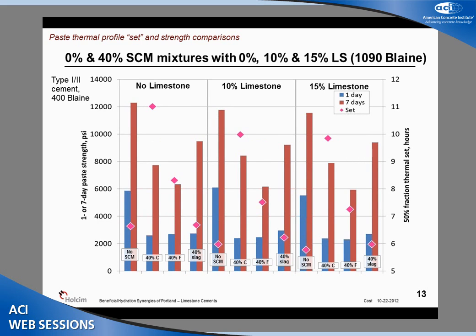Later on, we included some slag cements in some different studies, and we were also interested to see what the effects of not only 10% limestone systems, but up to 15%, what that would be. And here is a similar mixture, a simulated mixture with 10% limestone of the finer grind that we had played with before, with 40% no SCM, 40% C ash, 40% F ash, and 40% slag. Now, I'm sorry, this is without the limestone. This is with the 10% limestone as we had done before, and this is at 15% limestone. And you can see that even at 15% limestone, in general, we're at least equal to, and in many cases, outperforming the system without limestone included.